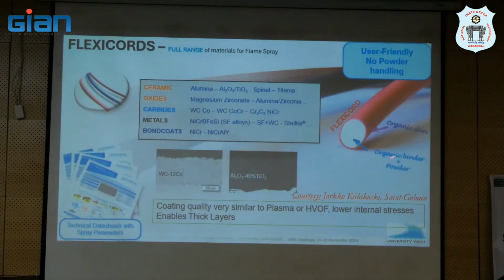We are very excited about this FlexiCord because just 2 weeks back, on my way to India, Saint-Gobain launched something called cord plasma spray, and that's a result of all the work that we have done in our lab with their FlexiCords. It's the first time that we have shown that even using a cord like this with zirconia, you can get columnar structure, right? That's a big thing right now. For us to be able to get columnar structure with a cord like this, nobody's shown that before, right?